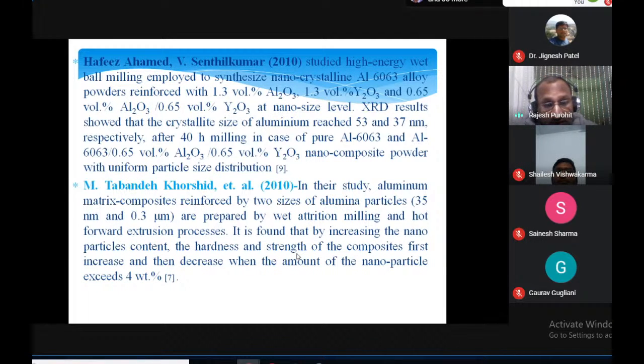Then similarly, other author Tabandeh Khorshid et al. In their study, aluminum matrix composite reinforced by two sizes of aluminum oxide particles, 35 nanometer and 0.3 micrometer. Nano and micro both are compared basically, prepared by attrition milling. So attrition type of ball mill was used, and hot forward extrusion process was used to manufacture. It is found that by increasing the nanoparticle content, the hardness and strength of the composite first increases and then decreases when the amount of particle exceeds 4 weight percent. So as I told, up to 4% we get better property, and then after 4% the property gets deteriorated. The reason is basically agglomeration of particles takes place and improper mixing, and especially particles are not mixed above 4 weight percent.